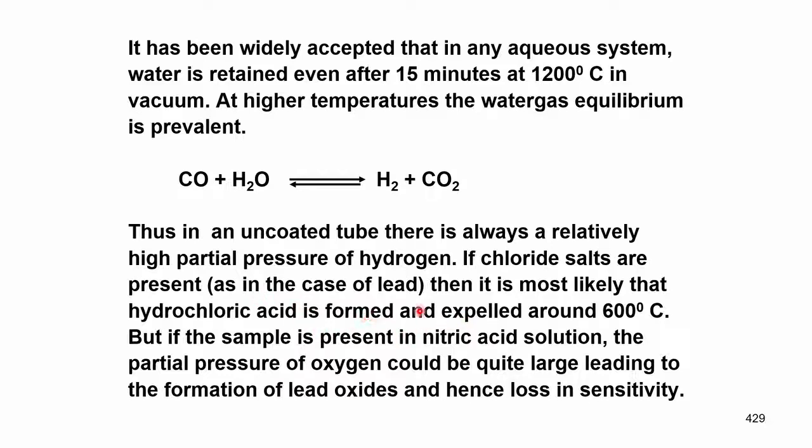But at lower temperature hydrochloric acid is expelled by about 600 degrees centigrade. So, the idea is whenever you have chloride salts, treat them around 600 degrees, hold them for some time, let us say 5 seconds or 10 seconds, then go for atomization.